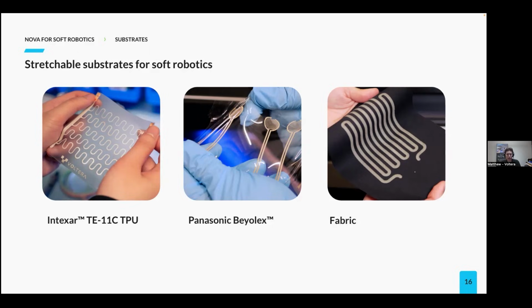And finally, I want to highlight that Nova can actually print directly on fabric, which can be useful for developing sensors and electronics in wearables, as well as coverings for soft robotics. There are a couple of things to keep note when printing fabric on Nova. We find that backing the fabric with material like Kapton tape allows the vacuum module to apply suction to the fabric. If it didn't have that backing, it wouldn't be held down. And then finally, we find that fabric also requires multiple passes of ink so that all that ink can soak into the fibers and build up a functional layer resistant to that stretching and deformation while still maintaining conductivity throughout the traces.